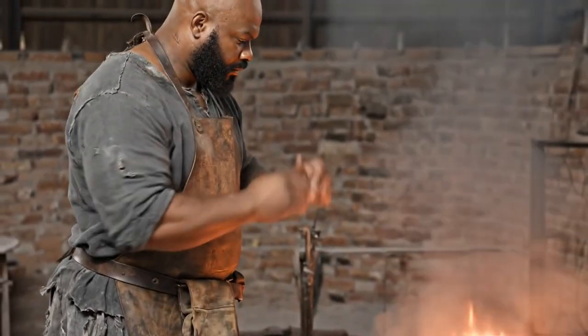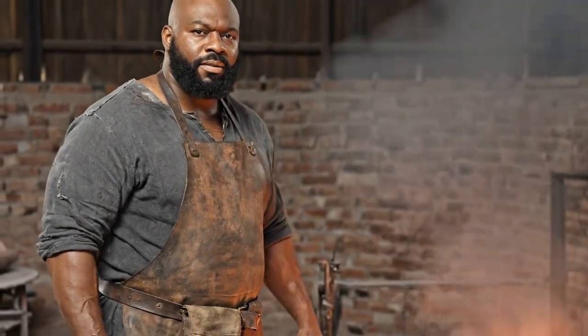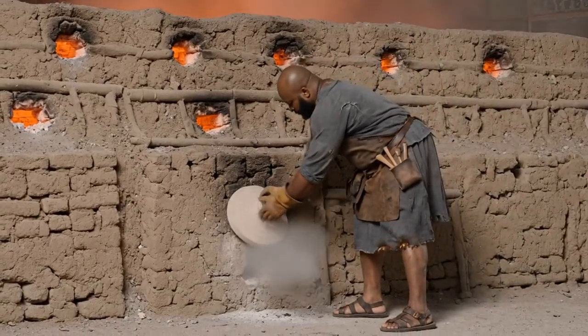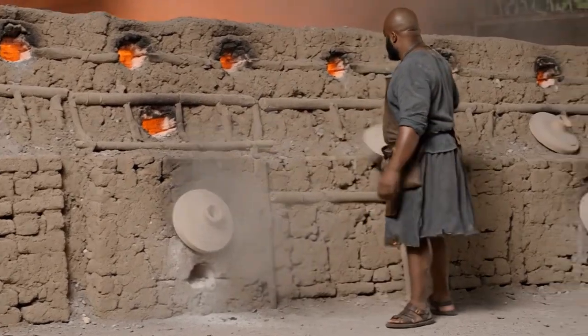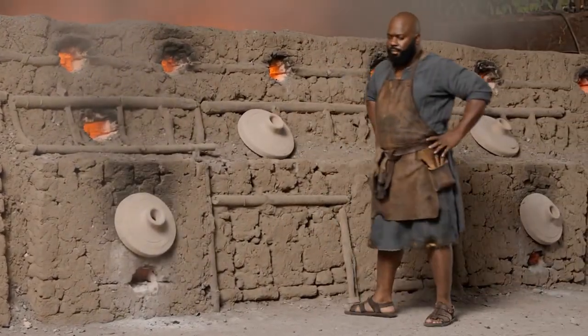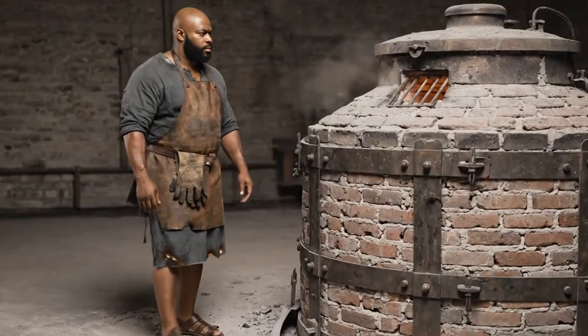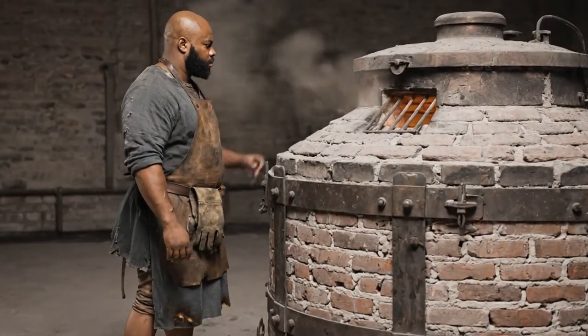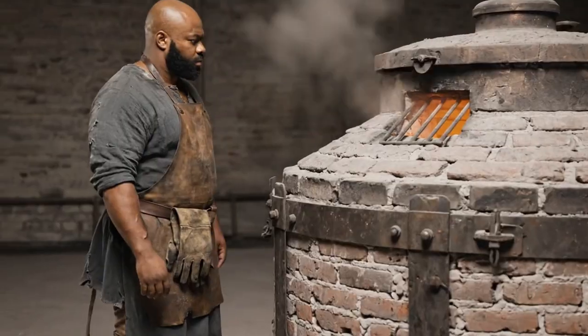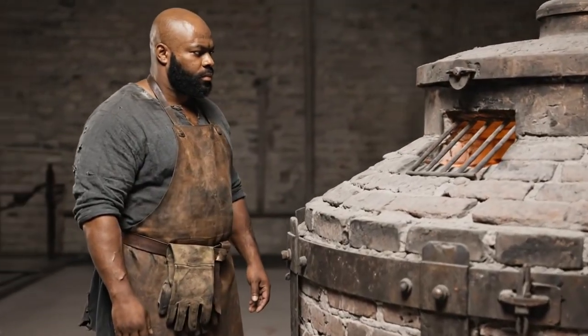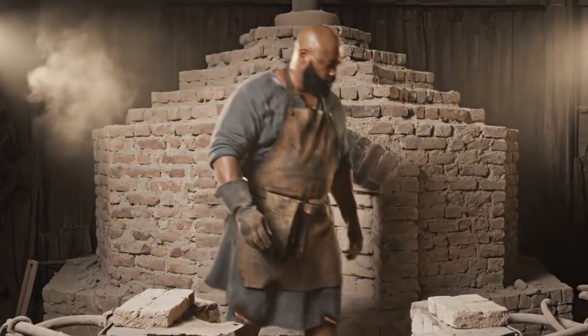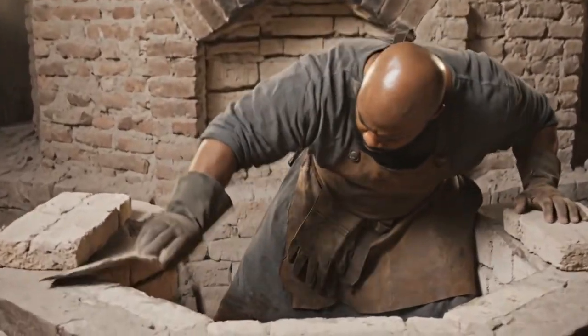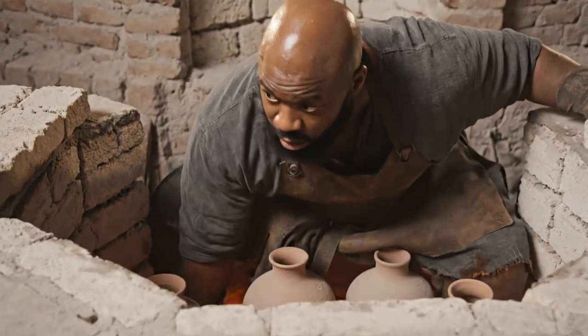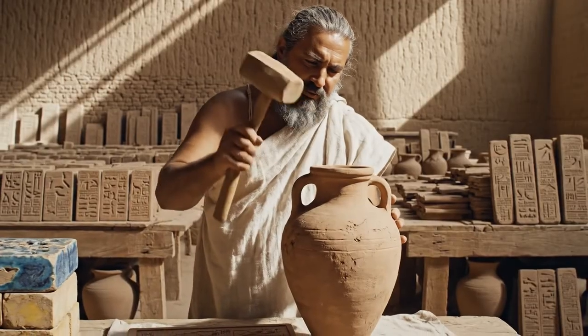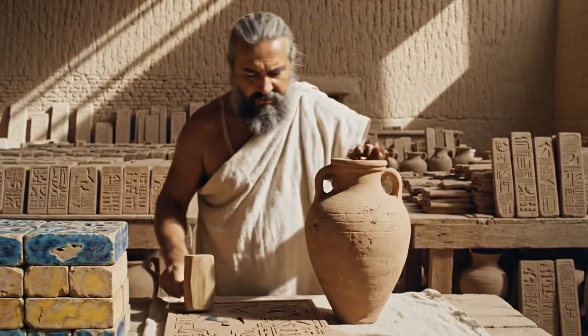When the firing is complete, they're sealing all the vents and letting the kiln cool slowly over 3 to 4 days, because rapid cooling causes thermal shock that cracks bricks just as effectively as rapid drying. And finally, when the kiln has cooled enough to touch, workers are unloading it. And this is the moment of truth, where they discover whether this firing was successful or whether they've just spent days and enormous fuel resources to produce 3,000 expensive pieces of garbage.